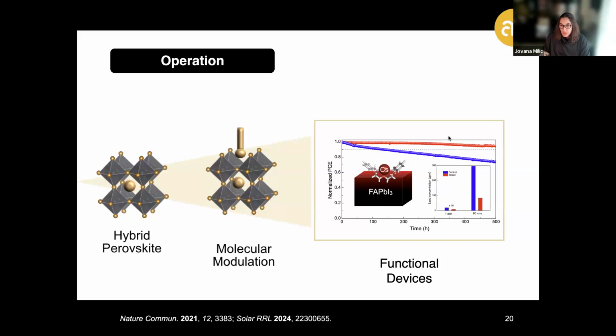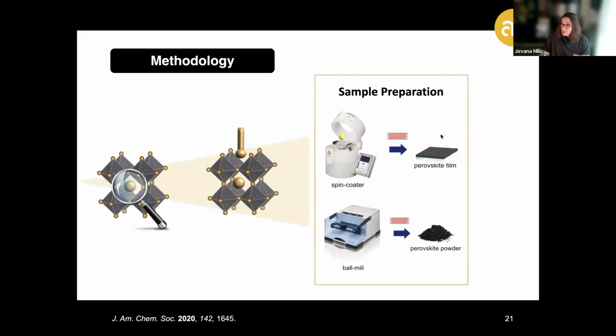This is possible by analyzing these systems systematically in both perovskite thin films and mechanosynthetic powders, prepared either through solution processing—straightforward approaches like solution-based spin coating followed by annealing to remove residual solvents—or by fully ball milling the precursor elements to form the resulting materials, which can then be analyzed by a series of complementary techniques to identify these effects.